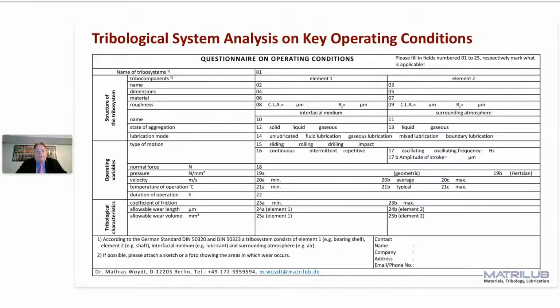The most widely used alloy in tribometry is ball bearing steel 52100 or 100Cr6. But if you have special applications, you really should consider producing your specimen from the alloys you have in your application. The tribological characteristics are important in many ways because you must define what range of coefficient of friction you would like to have, what gap increase you can accept, and having this gap increase, you define when you expect the loss of the function. From this, you can calculate the wear volume, and with the other properties, you come to the wear rate.